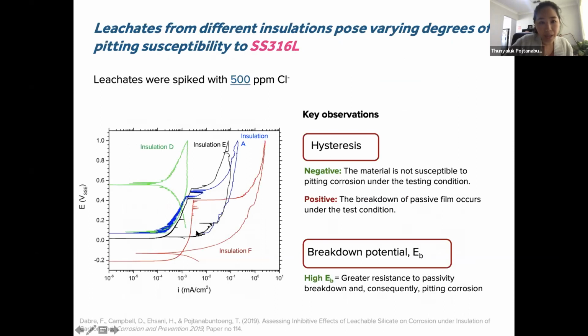So in this case, we look at 4 different insulation materials from fresh insulation, and the leachates were spiked with 500 ppm chloride. The reason that we spike with some chloride is, first, to enhance the conductivity of the solution, and second, a past project where we obtained the insulation from the field shows that over time chloride will enter the system anyway, and therefore introducing chloride is not unrealistic. And what we can see here is that different types of insulation material can lead to a different risk in terms of pitting susceptibility.